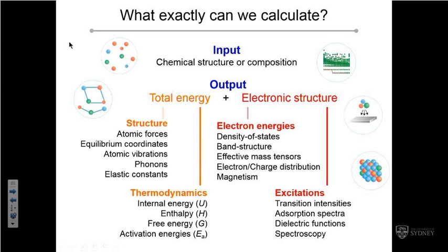Remember, the Fermi function at T equals 0 was, for a metal, a sharp step function. In the calculations, that can sometimes cause trouble, so sometimes you smear that out a little bit, and it helps to converge in this iterative cycle. And then you have to extrapolate back to 0 what you have done to your result. That's more of a technical thing that I shouldn't bother even mentioning. Never mind. Okay, and from the band structure, you can calculate various optical properties. Okay, and you can compare with experiment and so on.